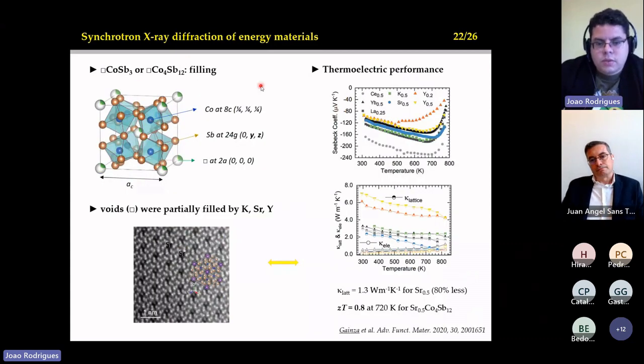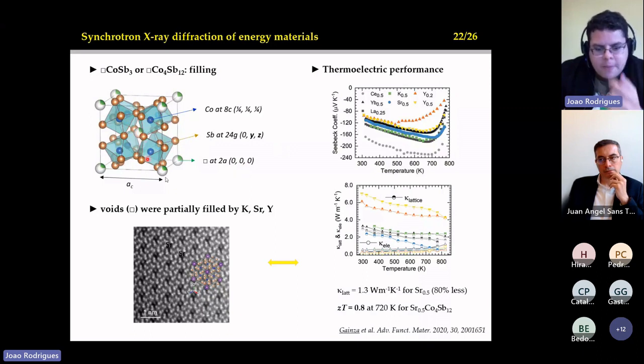And then here is a result that we have. We have the skutterudite based on cobalt and antimony, and we managed to put atoms in this void here. This is the octahedra made by cobalt and antimony. In the middle of these octahedra, there is a void in a crystallographic site. And the idea is to induce, under pressure, the filling of these voids.